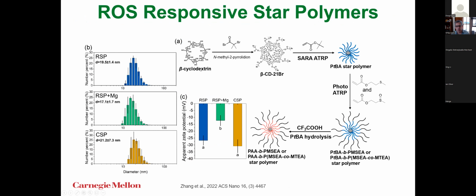This gives you an idea of the synthesis procedure. I won't go through that in all detail, but it similarly starts with this beta cyclodextrin. We grow all these polymers, and we make this diblock polymer that has what we need in terms of the two blocks, the MSEA and MTEA. And then we load them with magnesium.